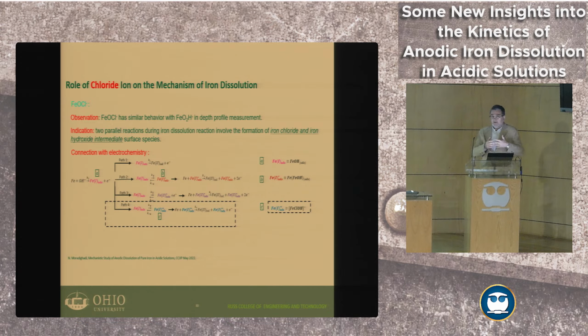If you have very little chloride, that may be irrelevant, but if you're in salt waters, 3%, that's a lot. Then, if you have 20%, it's absolutely dominating. The surface is totally covered with chloride, not hydroxide. So it makes a huge difference, and the kinetics of iron dissolution will respond accordingly.